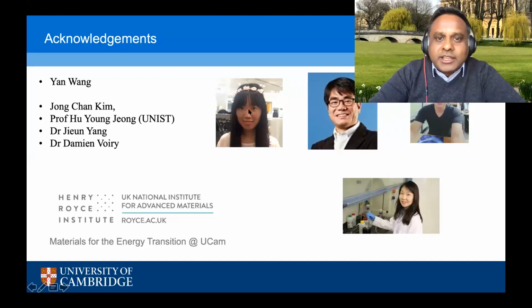There was a question: is there any 2D layered material with mostly ionic conductivity rather than electronic? What kind of functionalities can such a material add to the 2D community? That's a good question. Ionic conductors are, of course, very important. The kinds of 2D materials that I was talking about do not exhibit any ionic conductivity. But in the battery field, there are several different types of layered materials, mostly oxides. For example, niobium tungstenate exhibits very good lithium ion conductivity. In fact, it becomes superconducting when you put enough lithium in. So if we can have ionic conductivity in some of these 2D materials, that could also be very useful for electrochemistry applications.